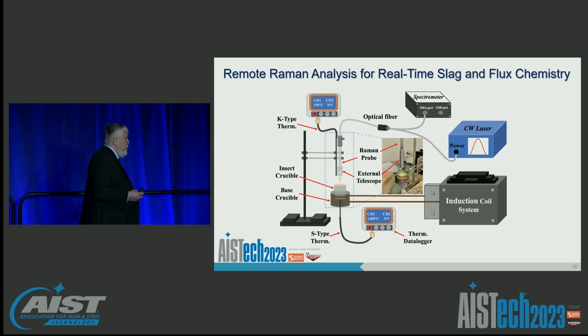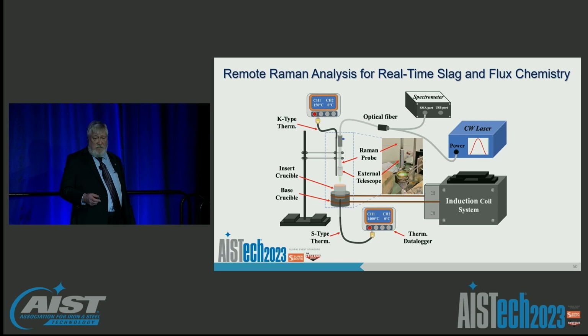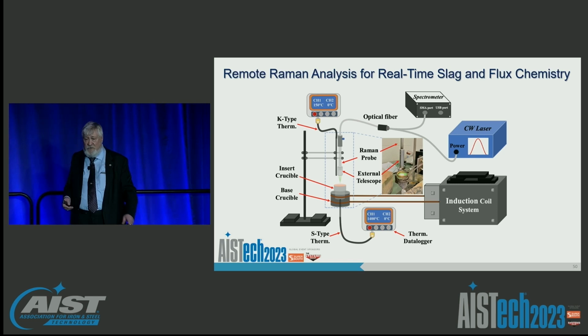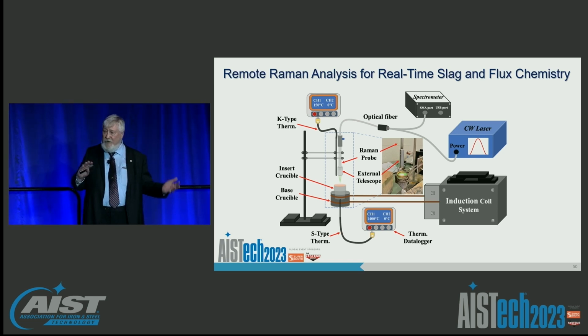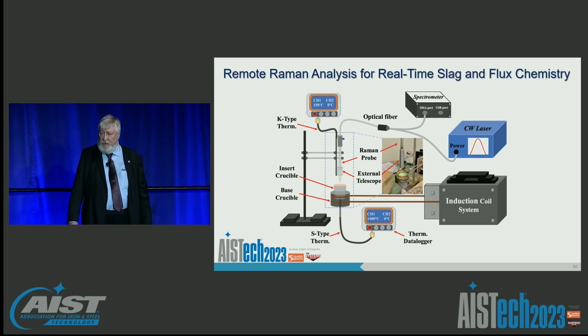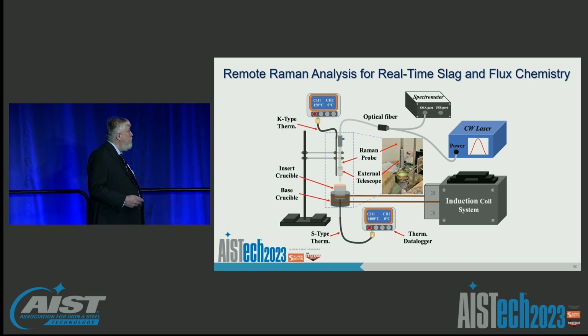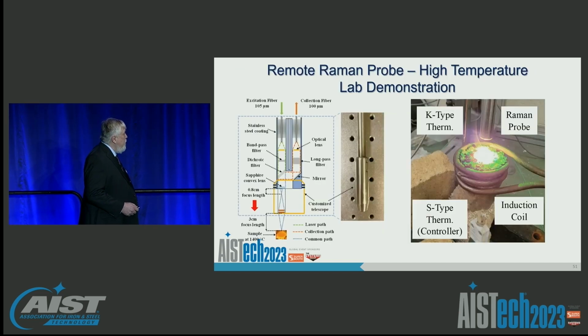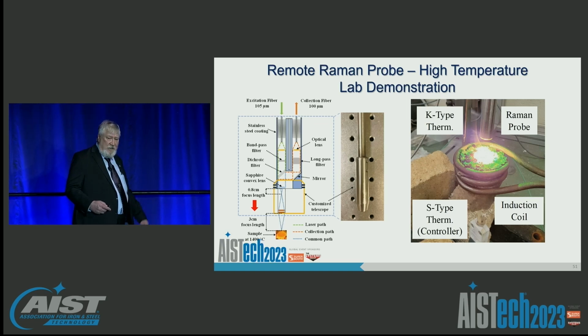Our first study on this was actually to look at mold fluxes and determine whether we can develop a probe that might be able to detect the shift in composition for some of the exotic steel grades we're trying to make, such as Generation 3 advanced high-strength steels, which have exchange reactions that cause actually pretty tremendous shifts in the composition of the flux. So this is actually what that probe looks like, and one of the small test conditions that we use in the lab to at least extract the Raman spectra and begin to understand it.